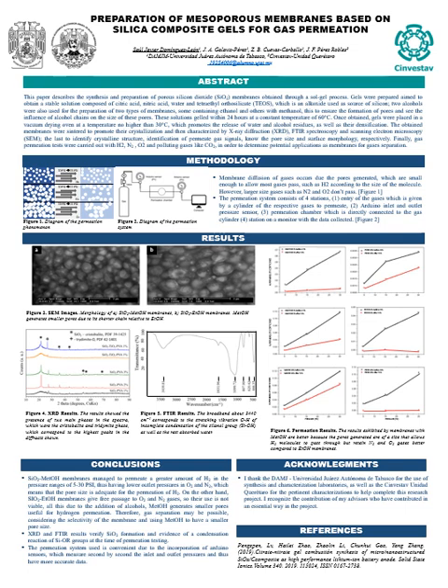The resulting solution solidified over a 24 hour period at a consistent temperature of 60 degrees centigrade. Subsequent to gel formation, they were introduced into a vacuum drying oven where the temperature was maintained below 30 degrees centigrade. This step facilitated the removal of residual water and alcohol, while also enhancing densification. Following this, the obtained membranes underwent a sintering process to encourage crystallization.